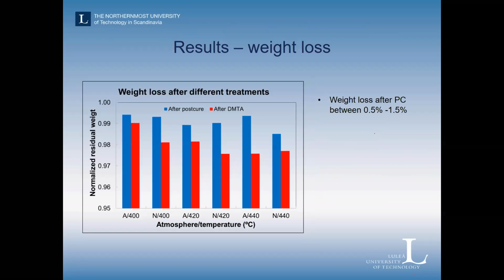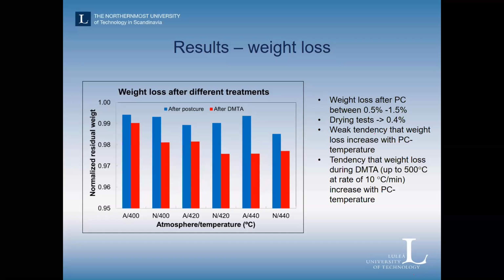Looking at the weight loss, we have immediately after post-cure in blue and after DMTA in red bars. We notice that the weight loss after post-cure is between 0.5 and 1.5%. We know that just from drying the material, we usually lose around 0.4 to 0.5%, so to a large extent this weight loss is because we're drying the materials. Then there's a weak tendency that weight loss increases with the post-curing temperature, but not significant. After DMTA, definitely there is a decrease, but that is rather expected since we're going up to very high temperature and we're doing it in air.